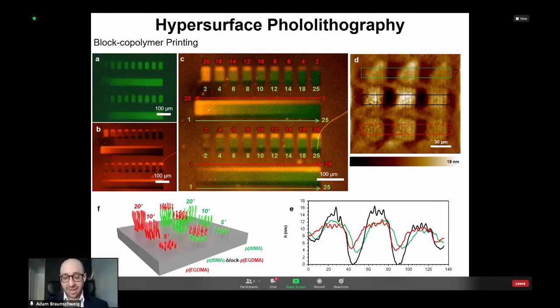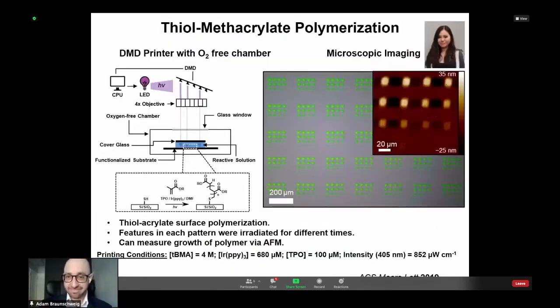So now any photochemical reaction you can do in solution, you can do on the surface. And in fact, the exploration of the different reaction conditions occurs much faster because in a single surface in a single afternoon, we can try hundreds of different conditions. That's illustrated here in work done by an undergrad at the time, Alexa Wong. And we were interested in exploring the thiol-methacrylate reaction. Here's a reaction popularized by Chris Bowman and Kristi Anseth in Colorado, except it hasn't been used at all to functionalize surfaces. And that's because it still remains relatively poorly understood compared to other reactions.